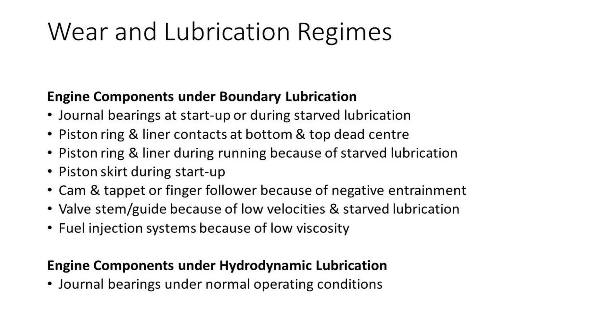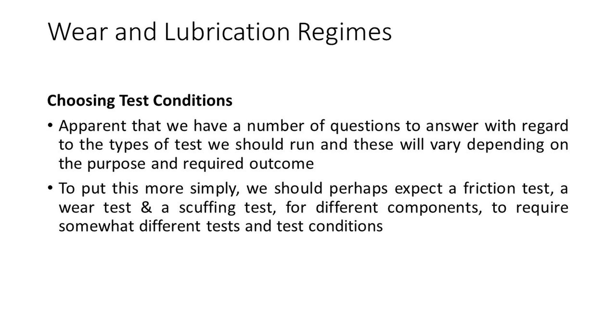Here are some engine components running under boundary lubrication: journal bearings at start-up or during starved lubrication; piston ring and liner contacts at bottom and top dead centre; piston ring and liner during running because of starved lubrication; piston skirt during start-up; cam and tappet or finger follower because of negative entrainment; valve stem guide because of low velocities and starved lubrication; and fuel injection systems because of low viscosity. Journal bearings run under hydrodynamic lubrication under normal operating conditions. We have a number of questions to answer regarding the type of tests we should run, which will vary depending on purpose and required outcome. A friction test, a wear test, and a scuffing test for different components will require somewhat different tests and test conditions.